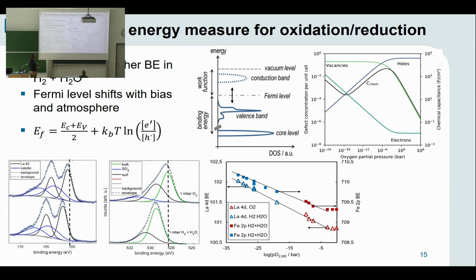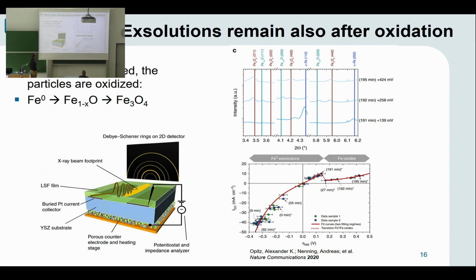Furthermore, we can measure the degree of reduction of the oxide in the XPS chamber, but I will skip this due to time. And by XRD data, we could show that the iron particles, once exsolved, remain on the surface, and they just transform into iron oxides, but they do not diffuse back into the perovskite oxide. So the reverse of the iron exsolution process is much slower kinetically compared to the exsolution itself.